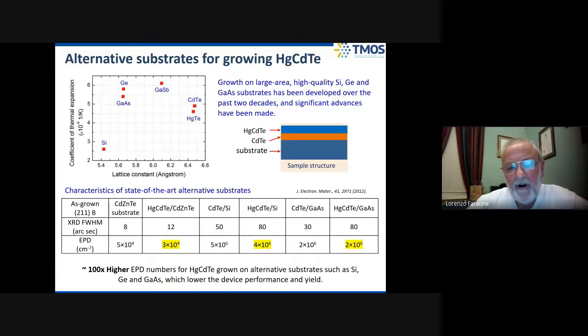So people have been trying to grow mercury cadmium telluride on other substrates such as silicon, gallium arsenide, germanium, gallium antimonide, etc. But notice that all these substrates, which are available in large area at low cost, don't match the lattice of mercury cadmium telluride. So that's a major technological constraint for this technology.